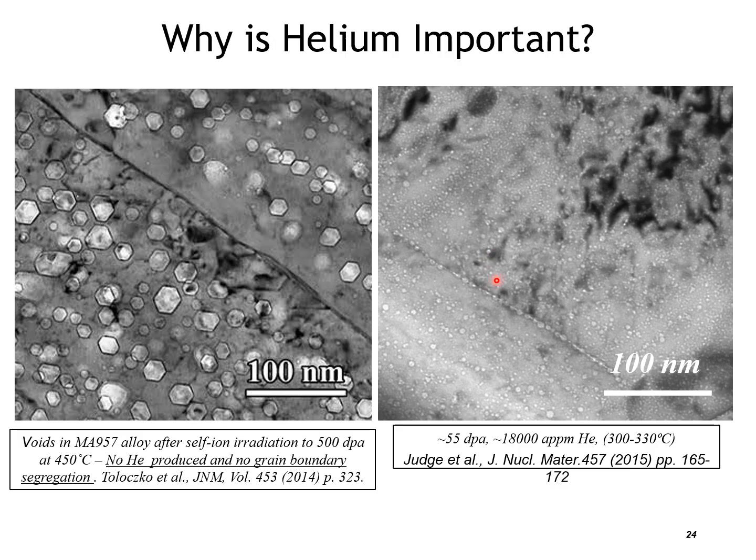But it isn't absorbed actually, because it's a helium atom and it's very insoluble. So it doesn't contribute to climb of dislocations in the grain boundary. So basically it migrates to the boundary and sits there. But because it has a high pressure, it then absorbs vacancies readily, and the surface energy of the resultant bubble can be lowered by absorbing more vacancies.